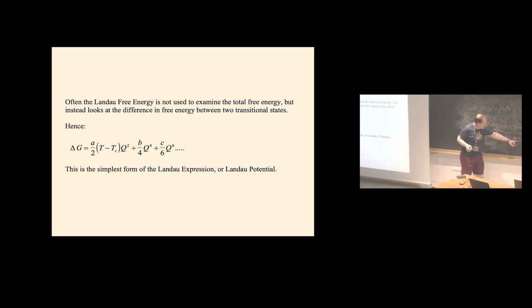So T minus Tc is Tc minus Tc, that's 0. So now you've got minus B plus or minus square root of B squared. Take the square root of B squared, you get B, divided by 2C. So now you have two solutions, minus B plus B or minus B minus B, because there's two roots to the square root of B squared.